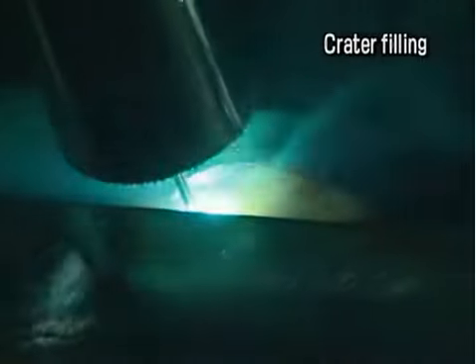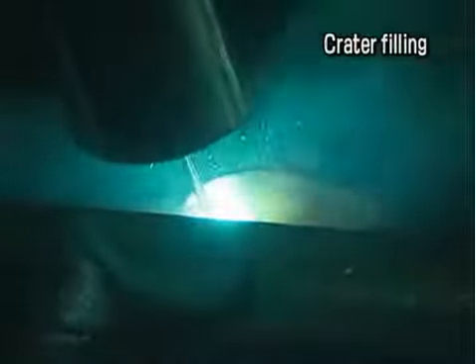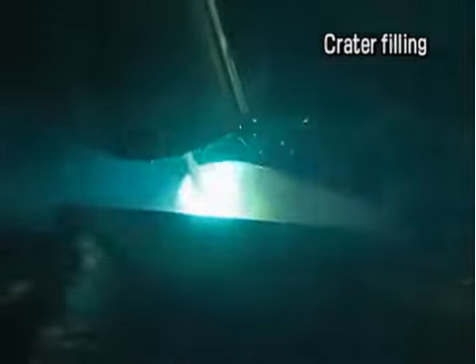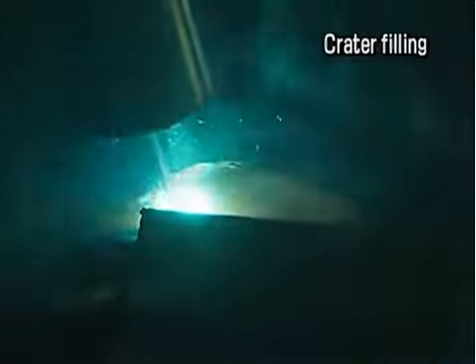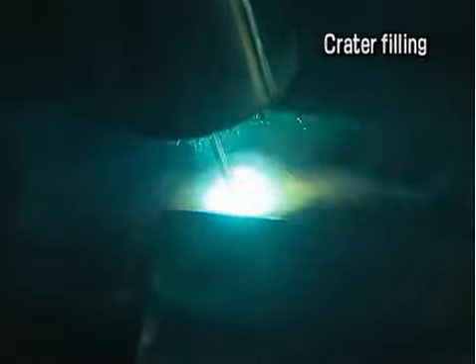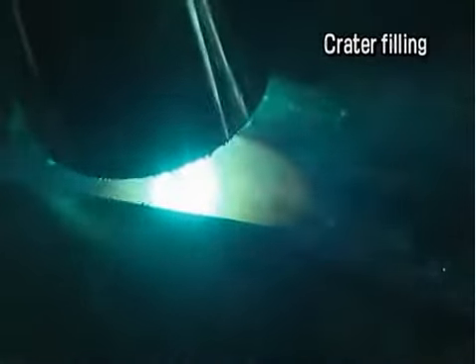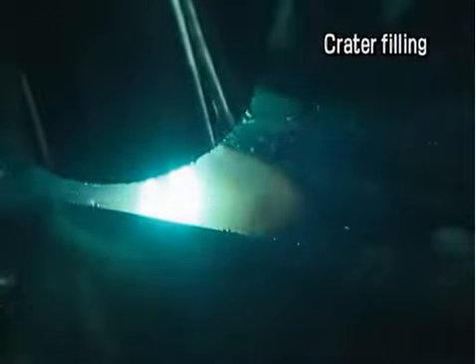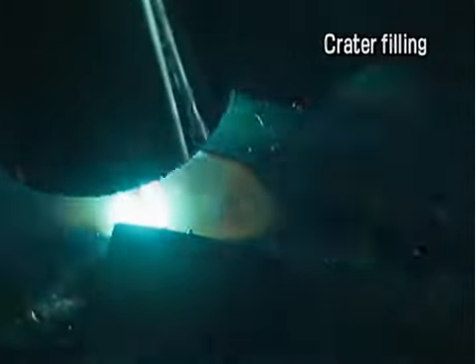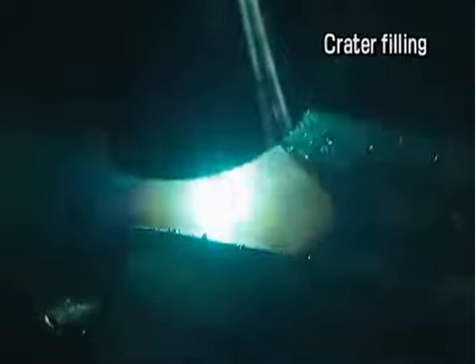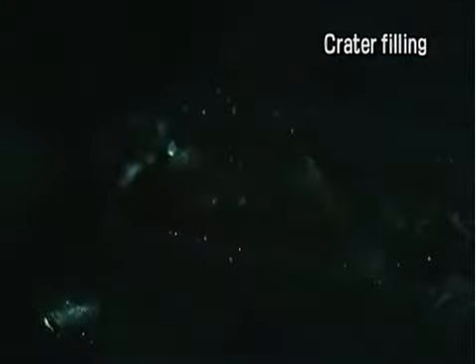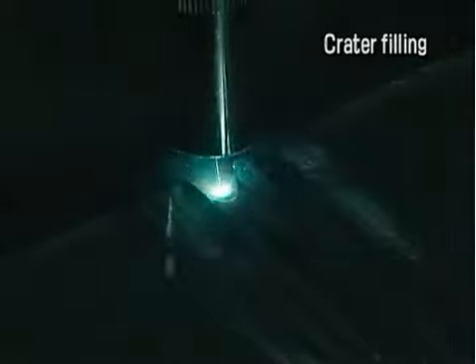One method is to stop the motion of the torch at the finishing point and strike the arc over the crater a few times for a half second to full second each time. This allows the weld pool to cool and fixes the dent while preventing burn-through of the weld metal. The other method is to stop the motion of the torch at the finishing point and move it slightly side to side over the weld pool or in a circle to fill in the dent. This should be done about 7 to 8 millimeters in from the end of the workpiece. It's also possible to combine the two techniques.